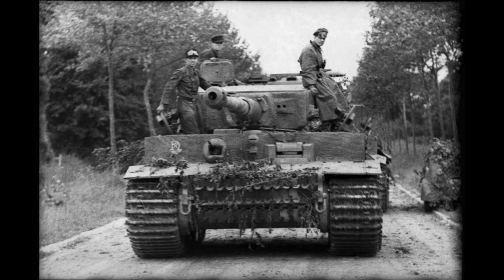This balanced approach prevented the armor from being too brittle, which would cause shattering under impact, or too soft, which would allow excessive penetration. Welding armor plate presented significant technical challenges. The high carbon content, typically around 0.4%, made the steel prone to cracking during the welding process. When heated to welding temperatures exceeding 1500 degrees Celsius, then rapidly cooled, the steel's microstructure could transform into brittle martensite. Cracks would propagate through the weld and into the base metal, creating weak points where armor-piercing shells could catastrophically defeat